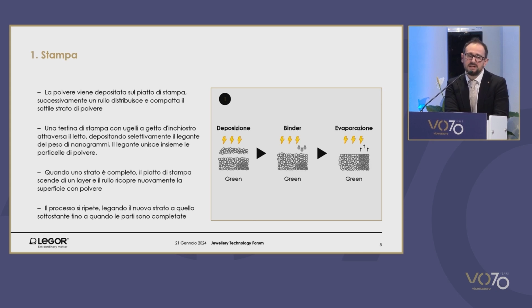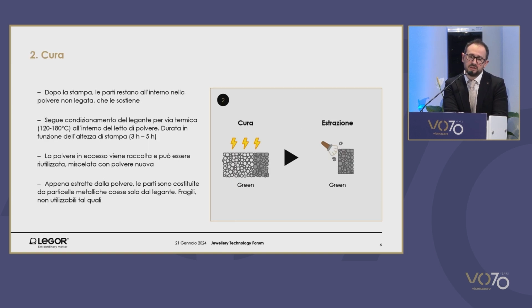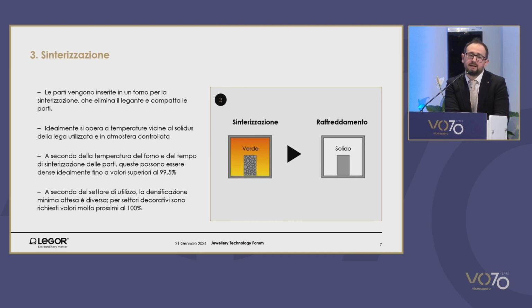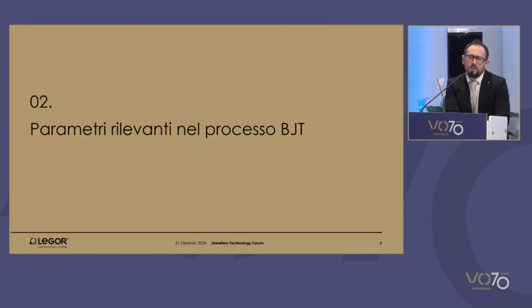These 3 slides simply summarize what I've just shown you. So, deposition of the powder, deposition of the binder in a selective way depending on the design of the item, where you need the structuring of the powder. Evaporation, that's a first phase to give mechanical resistance, which takes place directly in the printer. It's proprietary technology. Then the powder is cured, the item is extracted, and following sinterization, we have the cooling cycle.